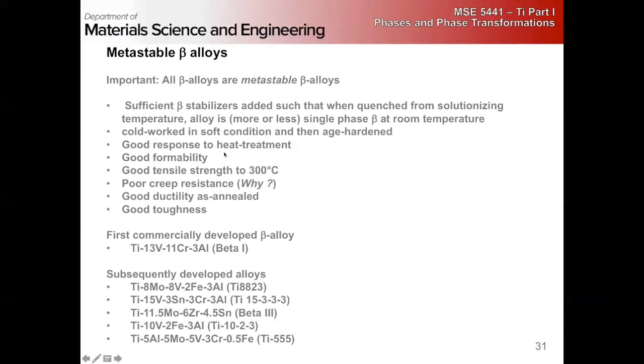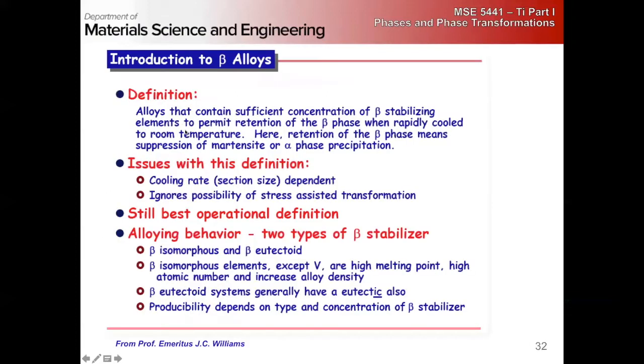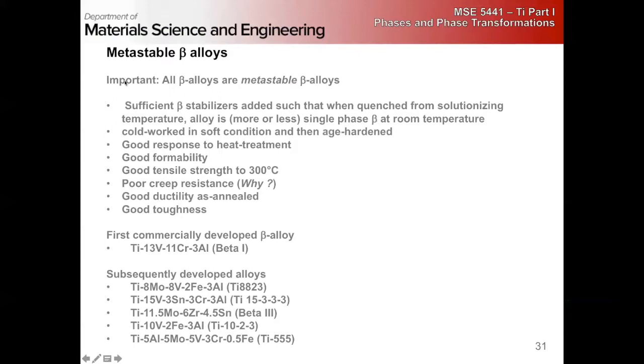Right? But in general, I think a good working definition is that if you can cold work it in the soft condition, right, quench it down so it's essentially full beta, have enough beta stabilizers in there to do that, they're typically cold worked and then age hardened to bring out the alpha. That's where I would personally draw the limit between alpha plus beta and beta alloys, right?